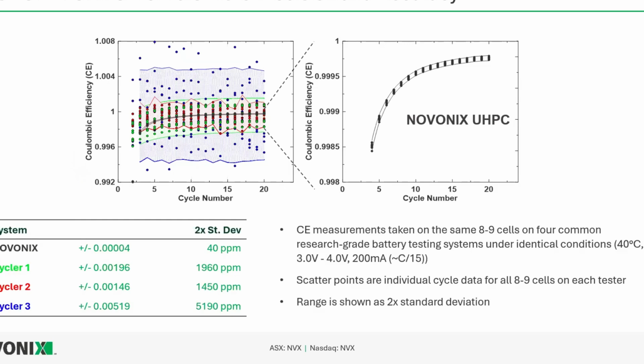So we can see here these other three cycler types that we have in our labs. We actually have thousands of channels of cycler 3 and hundreds of cycler 2, and then hundreds of our own cyclers. You can see the difference when we put on a group of identical tier 1 manufactured cells. This group on the Novonix UHPC has very tight Coulombic efficiency, very consistent, repeatable cell to cell. So this is really going to help us make these really accurate measurements very quickly and differentiate between cells. Because here, the noise and the inaccuracy of the cyclers is much, much bigger than the differences cell to cell, or even between a change that we may make to a cell. So we're going to lose that ability to differentiate between cells or chemistries with these other pieces of equipment.